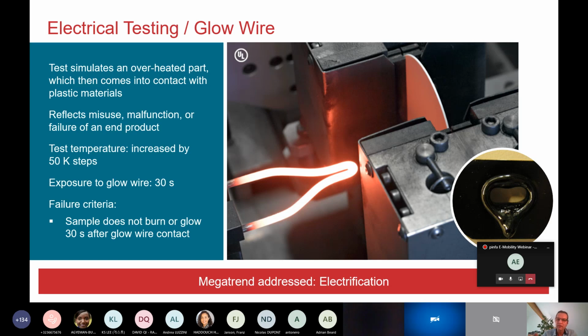You have failure criteria. On the right-hand side in that presentation, you see a sample which was melting in this case. There was a hole formation, of course, and some of the material was flowing down. And you look at the time the material is burning after the test. Once again, this is for sure a good basis to classify materials for connectors, for plug-in systems and the like, because you need to know how those materials behave when you have a misuse, a malfunction, or something which is not normal in the application.